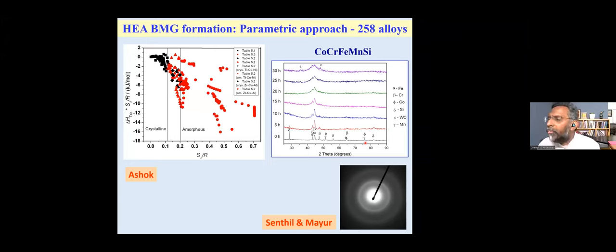The last few slides are to tell you that if the entropy of the alloy is very high, in principle, it should become amorphous. Because what is an amorphous material? Amorphous material is a random arrangement of atoms. Okay, there is no periodicity there. Such an alloy can be developed by this kind of a process of what is called high entropy alloys. So this is one such alloy, a five-component alloy, where if you choose the elements properly in such a way that there is a tendency for the alloy not to form a crystalline solid solution, but to form an amorphous solid solution.